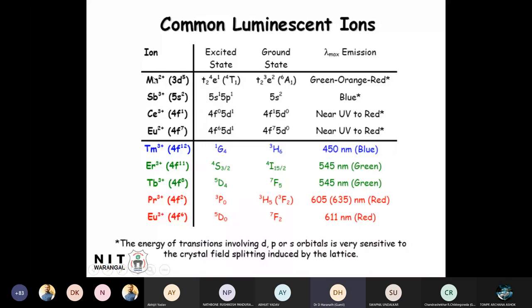In very few ions, it will show like this. Like antimony blue and cerium from UV to red, any color depending upon the influence, more towards red, less influence towards the left-hand side. But here you see there is another set of ions, dopants. They never bother about the crystal. Whatever crystal you dope them in, they have a fixed color, like thulium. In any number of crystals you dope it, it will never get influenced by the crystal, it is very rigid, and it will show its emission, that's it. Of course, the intensity may vary a little, less or more, but they are fixed colors, they don't change with the crystal.